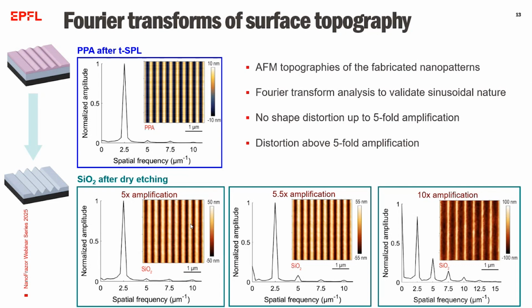However, at amplifications exceeding 5 times, we begin to see deformation of the sine waves, resembling mostly a U shape at 10 times amplification. So when we are patterning and designing our patterns, this effect must be considered, particularly when aiming for higher amplifications.